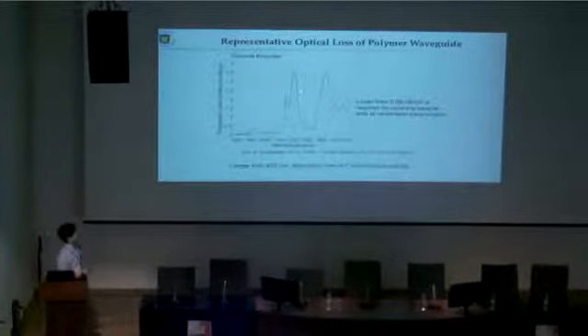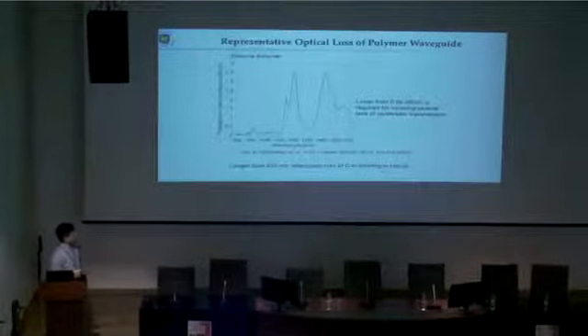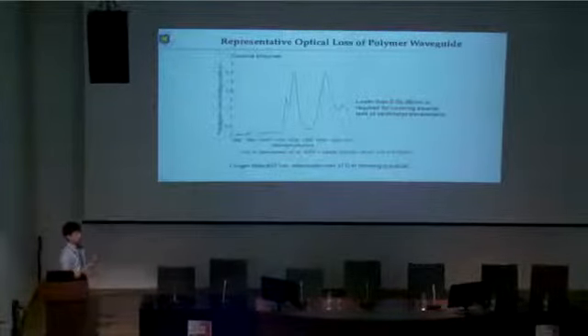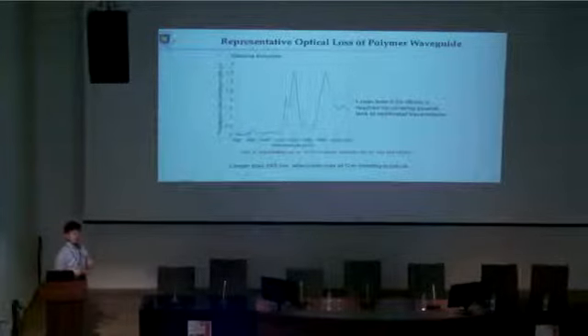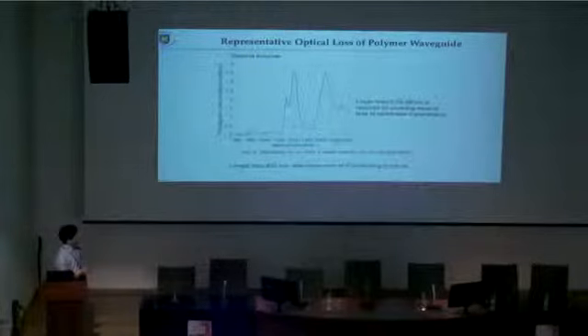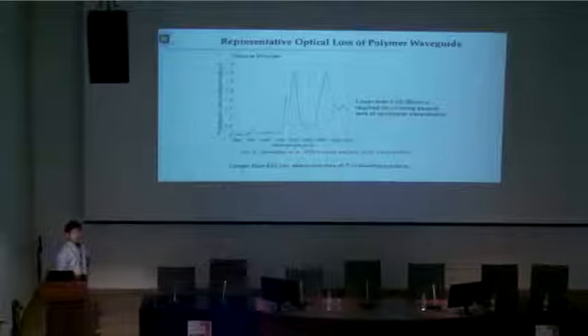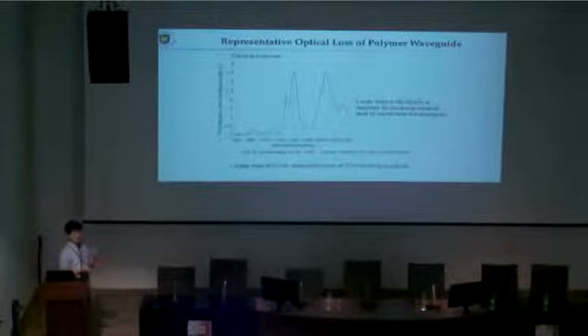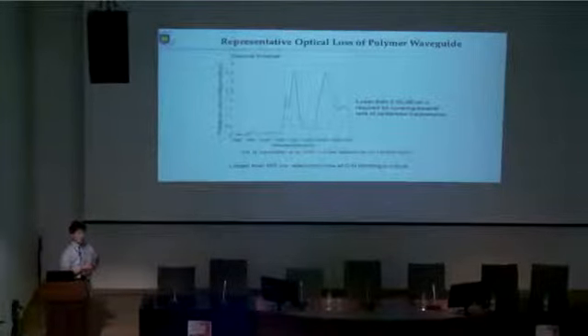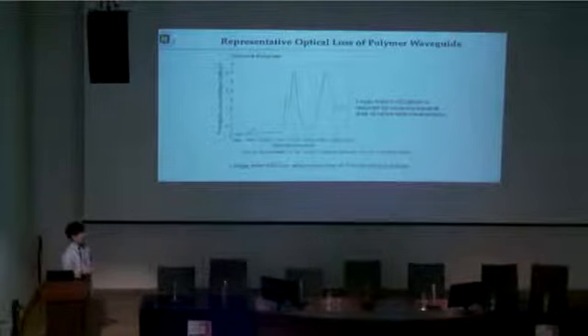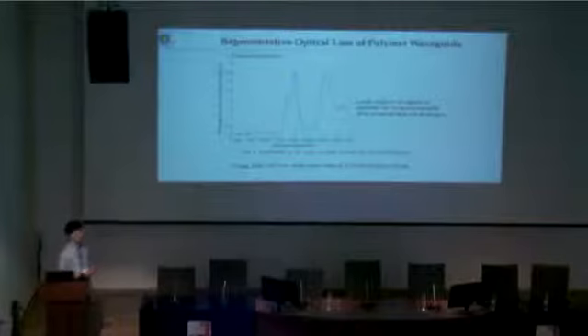And then this is a typical loss spectrum where at 850 nanometer, currently less than 0.05 dB per centimeter is required for at least a 50 centimeter long distance link. While you can see several peaks in the attenuation spectrum, that is coming from the absorption due to carbon hydrogen that is inherent in organic polymers. Therefore, as I mentioned, fluorinated polymer is a candidate in order to decrease this polymer inherent absorption loss. Because if we substitute carbon-hydrogen bonding with carbon-fluorine, because fluorine is a heavier atom than hydrogen, we can decrease the absorption. We can actually shift these peaks to longer wavelengths.